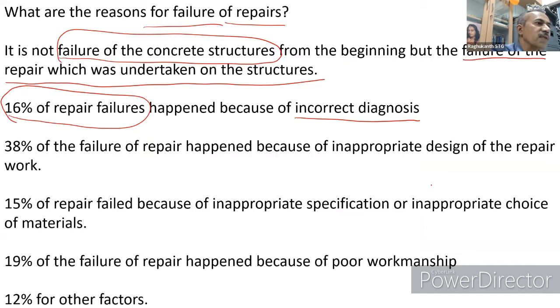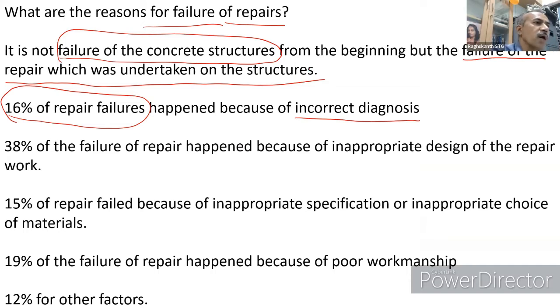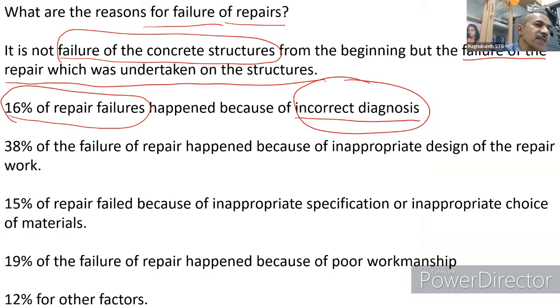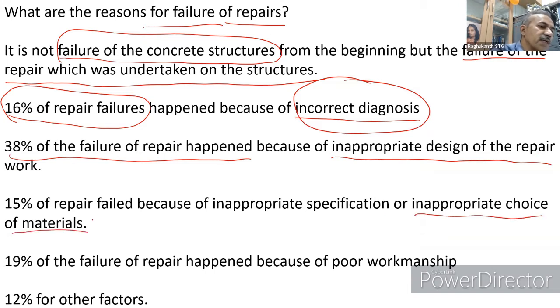Looking at the statistics: 16 percent of repair failures are due to incorrect diagnosis; 38 percent are due to inappropriate design of the repair work; 15 percent are due to inappropriate choice of materials; 19 percent are due to poor workmanship; and the rest are due to other factors.